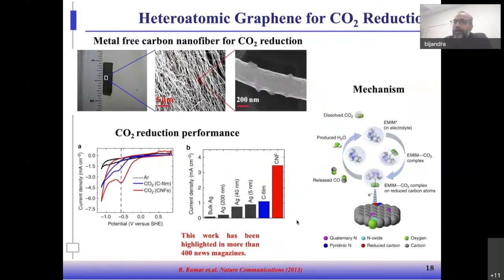So first is carbon-based heteroatomic graphene for CO2 electrochemical conversion. Initially, we developed these carbon nanofibers. And when we tested them, they were really great catalysts for CO2 electrochemical conversion. When we compare the current density and Faraday efficiency, they have almost 100% Faraday efficiency for CO formation, and at least 4 to 5 times higher current density compared to advanced Ag nanoparticles. Then we came up with the idea that when you introduce a nitrogen atom into this graphitic structure, there is a difference in electronegativity between the nitrogen atom and the carbon atom. Due to that difference in electronegativity, these nitrogen atoms can participate in the electrochemical reduction.